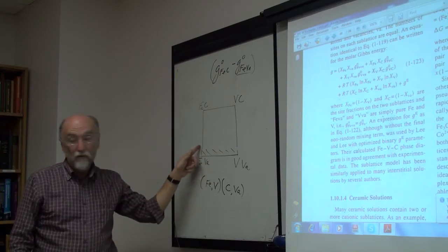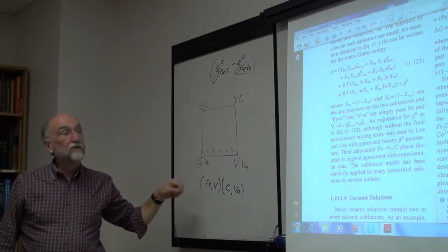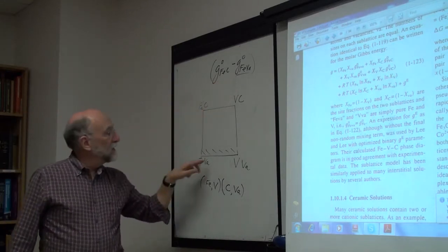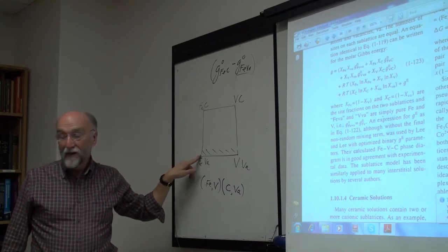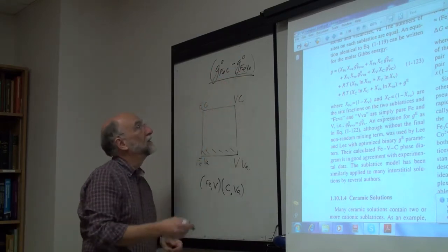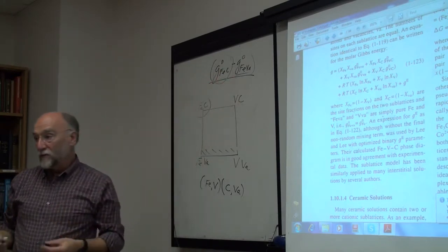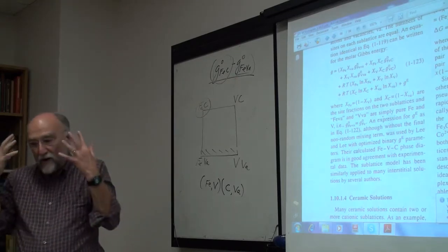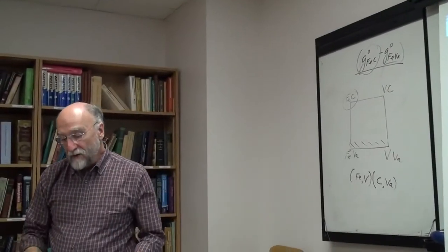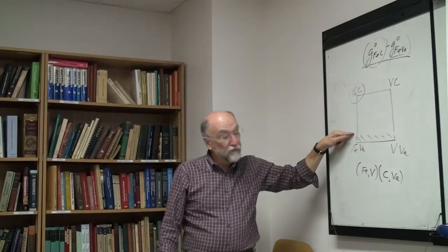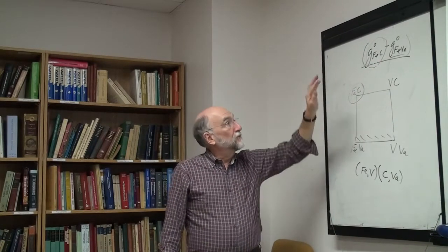It is really only meant to apply over the dilute solution. Okay, so it's sort of like a Henry activity coefficient, if you like. This is simply the energy of putting carbon into the vacancy, into the lattice here. So this is your model parameter. This I call the formalism parameter. This minus this is your model parameter. The real model is, what is the parameter that has a physical meaning? The parameter that has a physical meaning is this difference. It's the energy of putting a carbon into an interstitial site. It's only meant to apply over this region. Okay. That's your model parameter.